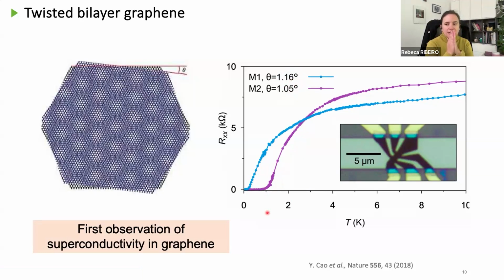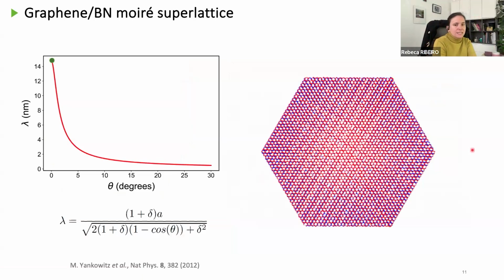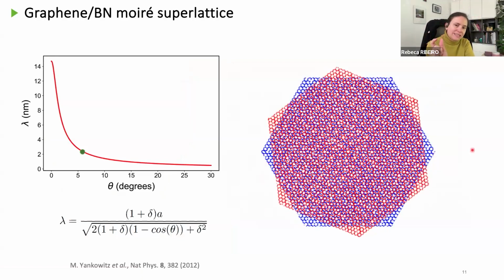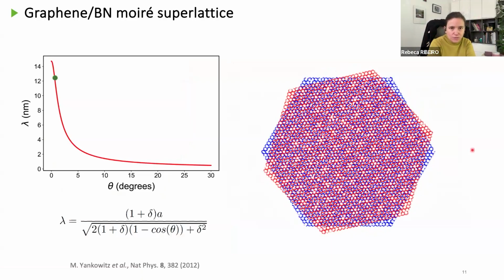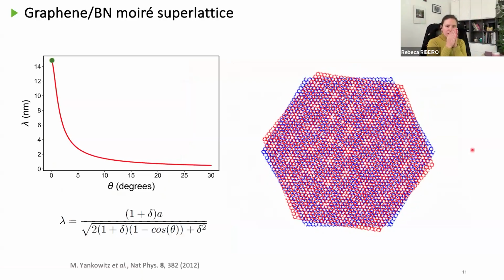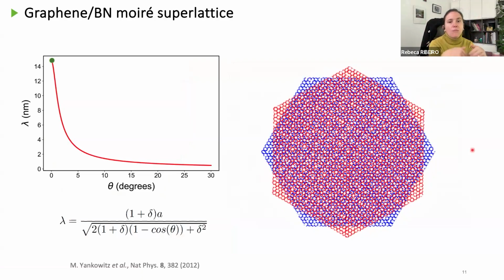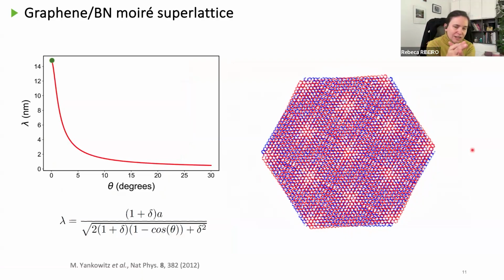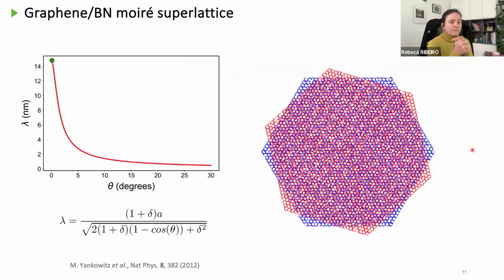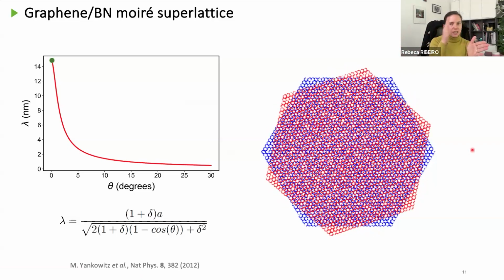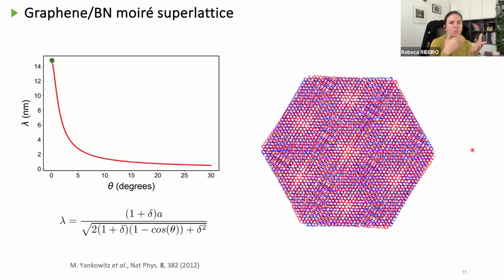So, okay, here is the example of two twisted layers of graphene. However, what I'm going to talk about is just one layer of graphene and a layer of boron nitride. And in principle, boron nitride is an insulator, so it should not modify the electronic band structure of graphene. Okay, but in fact, since the two lattice structures of graphene and boron nitride are so close to each other, when they are crystallographically aligned you have an effect called a moiré effect that you can see here. This is just an optical illusion. It's a representation of this moiré. But I'm going to explain in just a second a little bit more in detail how and why this moiré is created.